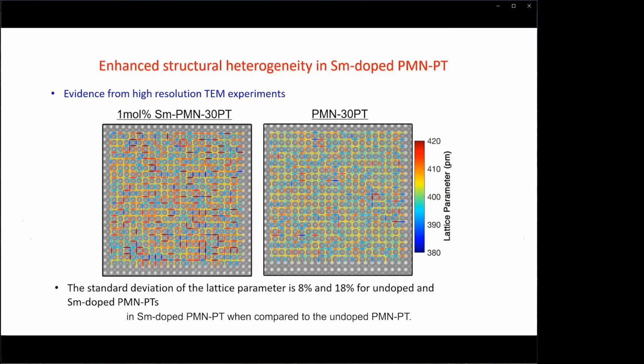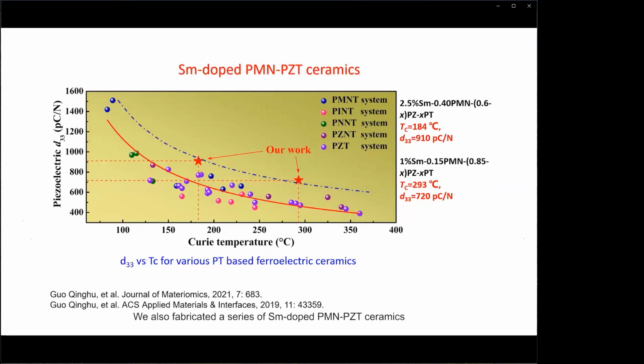We also fabricated a series of samarium doped PMN-PZT ceramics as shown here. Compared to state-of-the-art piezoelectric ceramics, samarium doped PMN-PZT show obvious advantages, especially for these two compositions. The piezoelectric coefficient d33 is 910 pC/N with a Curie temperature of 184 degrees centigrade, and the piezoelectric coefficient d33 is 720 pC/N with the Curie temperature very close to 300 degrees centigrade.